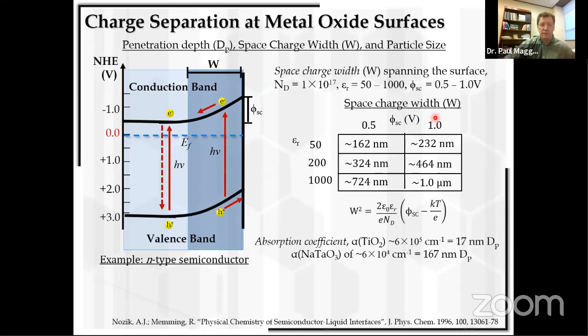And so here's just a simple schematic of how the valence band and the conduction band of an N-type semiconductor, what's called bend at the surfaces when the chemical potentials of the semiconductor equilibrate with the chemical potential of the electrolyte. And so you see that they're bent up as the electrons, right? If you have an N-type semiconductor, you have excess electrons doped in the material, and they empty out at the surfaces somewhat, and those bands bend.